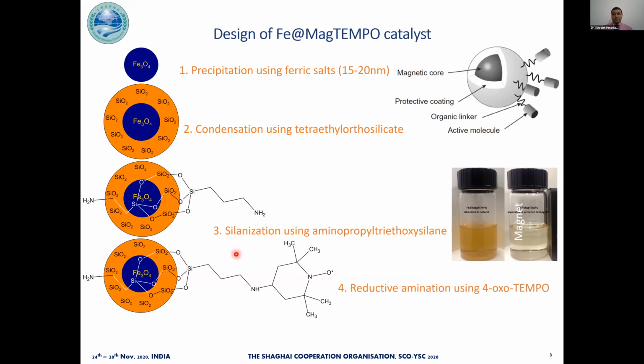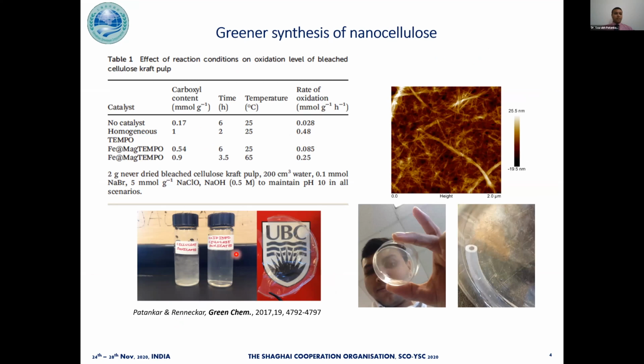I was able to synthesize nanocellulose with the same properties as the one made from the usual homogeneous or free TEMPO process. Even the rate of reaction with the TEMPO anchored on nanoparticles was similar to the free TEMPO reaction rate, albeit at a slightly higher temperature. We further used this sustainable nanocellulose, which was made using this new heterogeneous catalyst, to make these tubes, which can further be used for some biomedical applications.